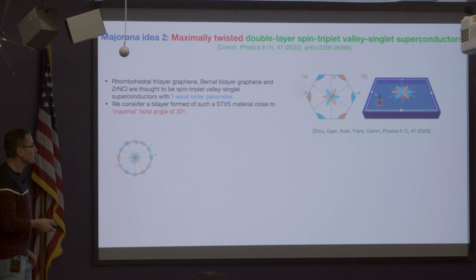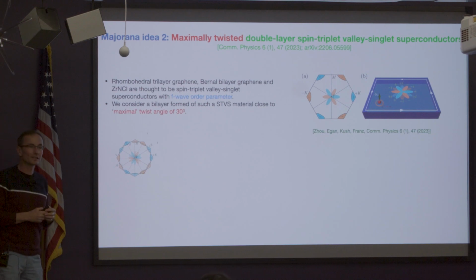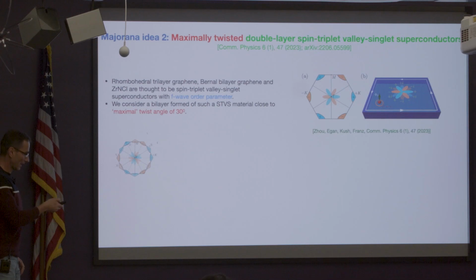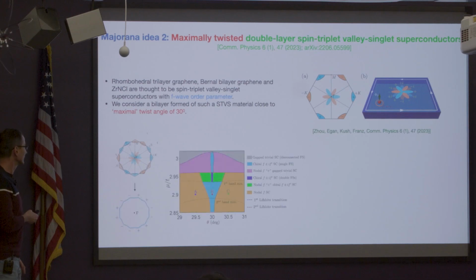So yeah. Anyway, he set up the whole Bistritzer-MacDonald calculation with the superconducting order, and here's the result of that calculation. This is the phase diagram. The axes are the twist angle and chemical potential. And there are many different phases, and I will not really describe all of them. So a large part of this, away from exactly 30 degrees, this orange is a nodal F-wave superconductor. That's when the energetics decide that the order parameter just remains real, doesn't break time reversal, and instead has nodes.